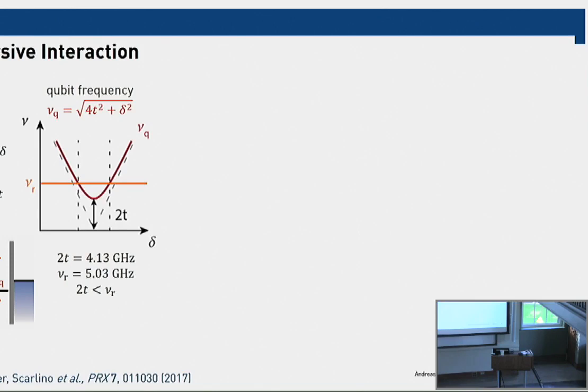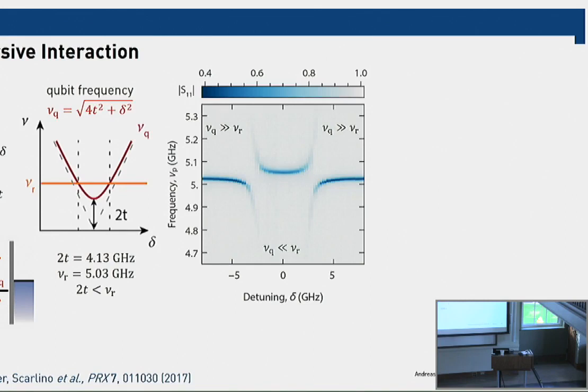And the minimum transition frequency occurs at the tunnel coupling. So the minimum level separation that you could realize is given by the strength of the tunnel coupling between the two dots. And now you can use this detuning of the local energy levels on the left and on the right to change the transition frequency of this double quantum dot. And if you choose parameters right, then you can make this double quantum dot energy levels get in resonance with the resonance frequency of the microwave frequency resonator. And here you would then expect the vacuum Rabi mode splitting to be observable.